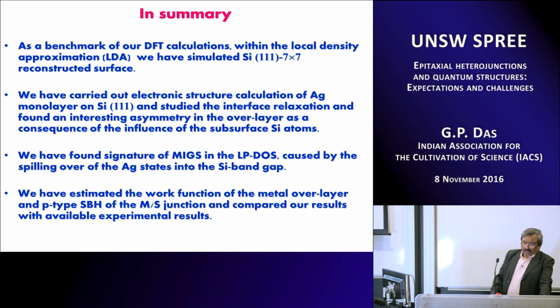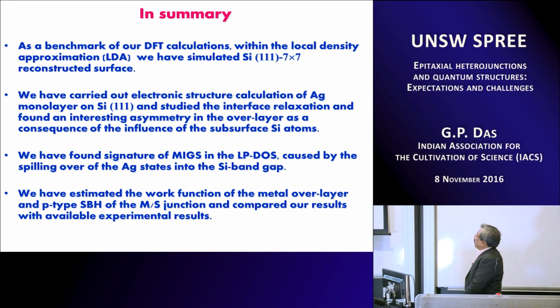So to summarize this particular part of my talk, I started with a benchmark for silicon 7x7 reconstruction, and then I told you about the interface relaxation and how the metal induced gap states appear in the layer projected density of states, and we have also estimated the p-type Schottky barrier height in the metal semiconductor junction. Okay.